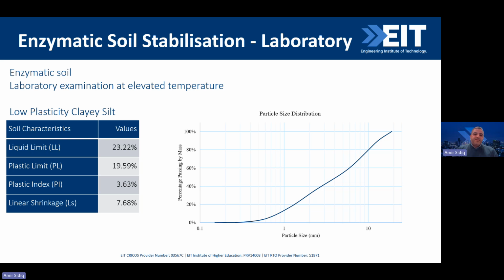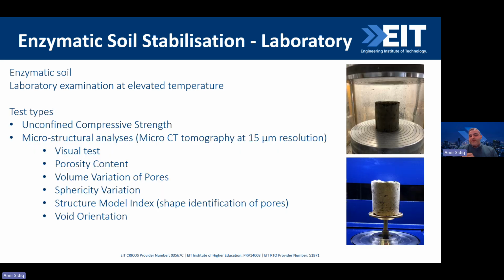And this is the particle size distribution of that particular soil. The tests I took were quite deep microstructural analysis using the micro CT. Initially, I did the unconfined compressive strength, which is known as UCS, and then the microstructural analysis I used at a 15 micron resolution.